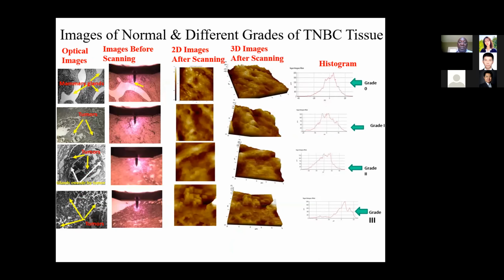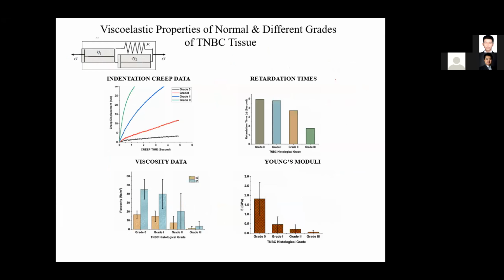We've looked at them with AFM techniques and light microscopy techniques that show that the morphologies of these structures change with grade. And you can also do indentation creep on those regions. And when you do indentation creep on those regions, you find out that the fastest rates for creep rates occur for grade 3 cancers. These are followed by grade 2 cancers in blue, and then grade 1 cancers in red, and then grade 0 normal tissue here in black.